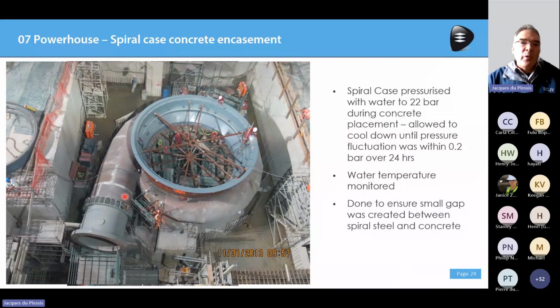So what was done on site was to pressurize this to 22 bars prior to concrete encasing it. And then after concrete encasement, the contractor monitored the temperature of the water inside the spiral case, as well as the concrete temperature. And when that fluctuation was less than 0.2 bar in 24 hours, and basically the water temperature inside the spiral case stabilized, the pressure was released, ensuring that little small gap around the spiral case. So just a very interesting part of the design that was followed out on site.